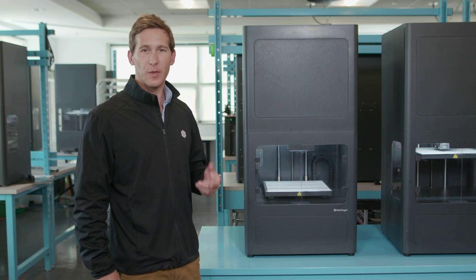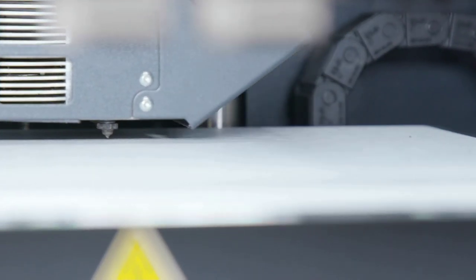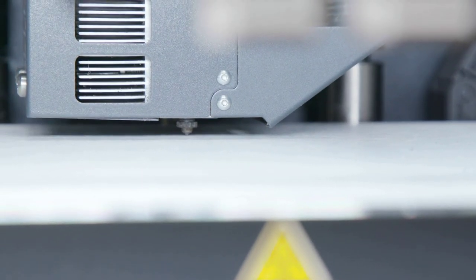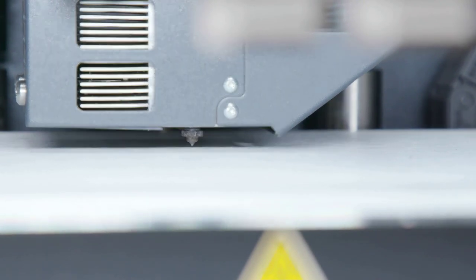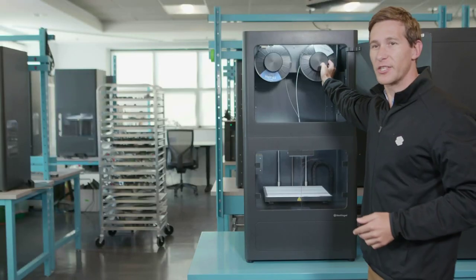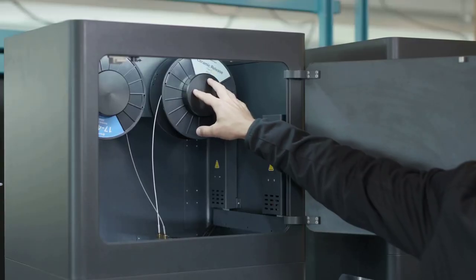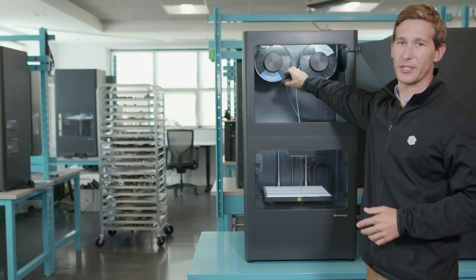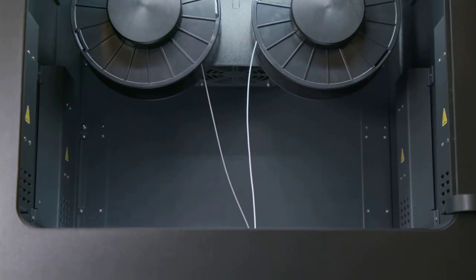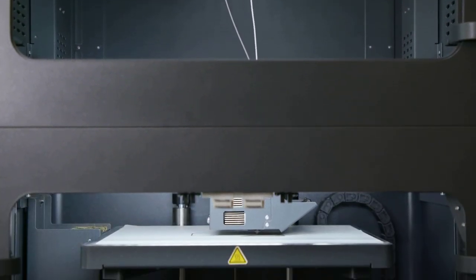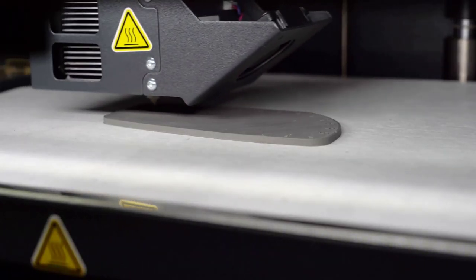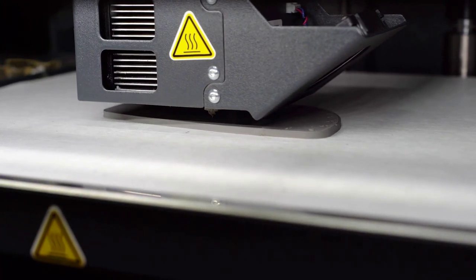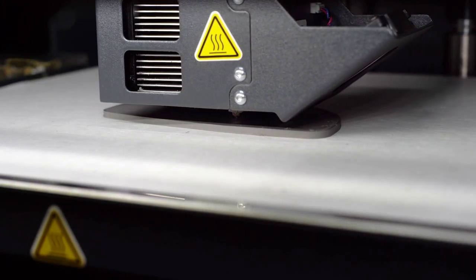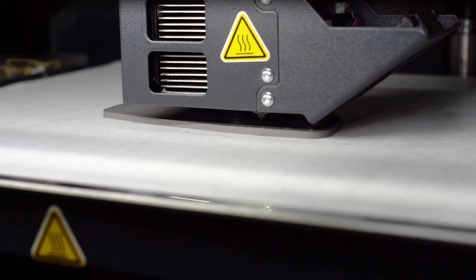Before starting a print, the machine automatically maps and levels the bed to ensure the first layer goes down well. Your print is built of 2 materials stored in this heated chamber above, one of ceramic release material and one of the metal to be printed. This filament material is metal powder safely suspended within a 2-part plastic binder. It gets heated and extruded onto the build plate where the part is created layer by layer. Release material gets extruded as an interface between the part and its supports, so that once your part comes out of the furnace, it's easy to remove.